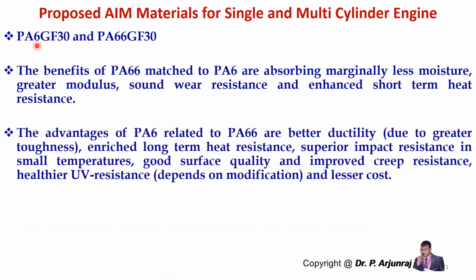And when you're comparing PA6 with PA66, PA6 is better for ductility because of its high toughness, and PA6 also has high long-term heat resistance when compared to the PA66 glass fiber 30. PA6 is also superior, having superior impact resistance at low temperatures, good surface quality, improved creep resistance, and better UV resistance, and the cost is also lesser when compared to PA66 with glass fiber of 30%.